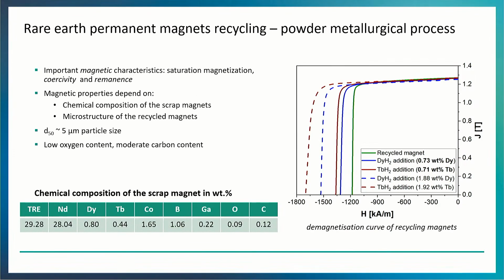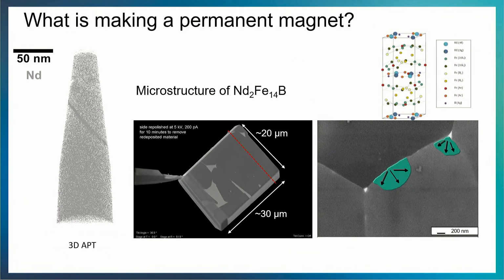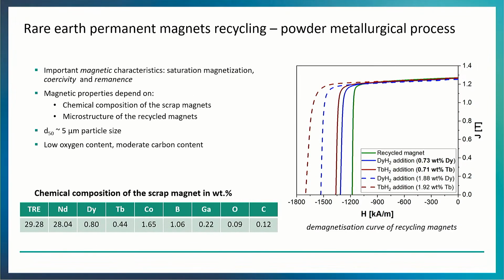But you need very good knowledge of the structure-property relationship to produce large, good permanent magnets, and therefore you need very good analytics, and we are using 3D atom probe tomography to find out about this grain boundary composition.